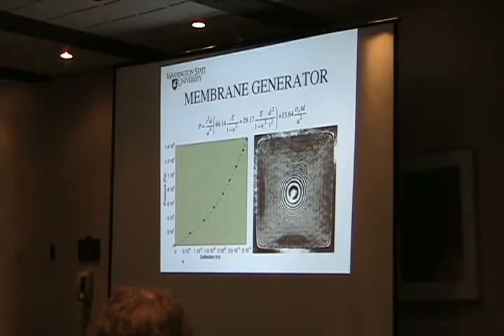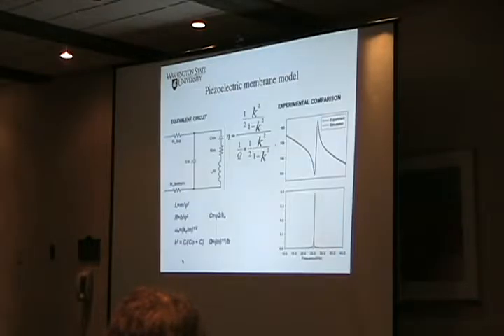So the way we started testing this was just making little piezoelectric membranes, and I'm not that smart, so I just pressurize them. We bulge test them and measure displacements and pressures and get a pressure deflection relationship. If we do that, we can calculate a residual stress in the films. Because we're trying to make relatively large wafer scale devices, we end up with relatively high tensile stresses, because I'm cheap and we tend to use thermal processing that's a little too high in temperature. But we can calculate all of that if we measure the pressure deflection relationship on one of these little membranes.